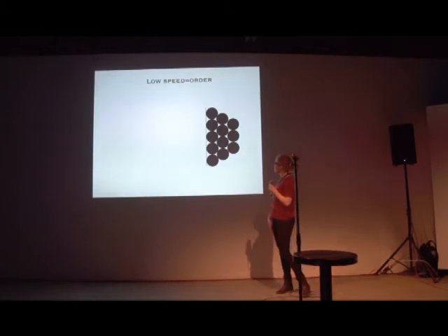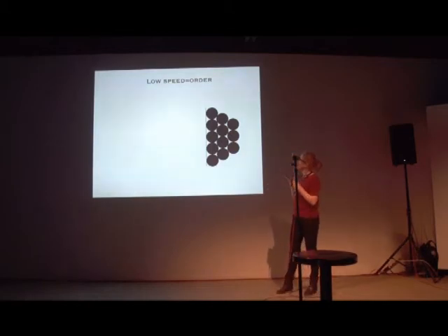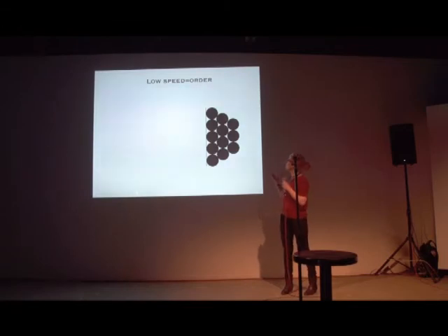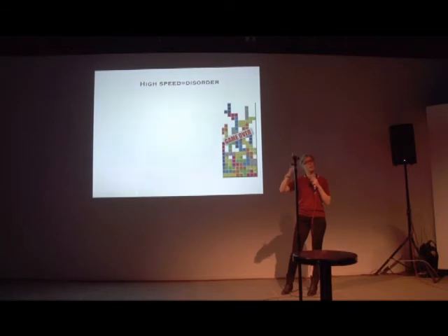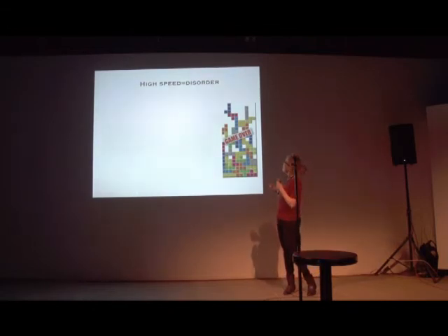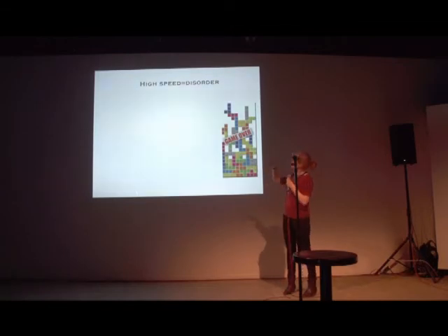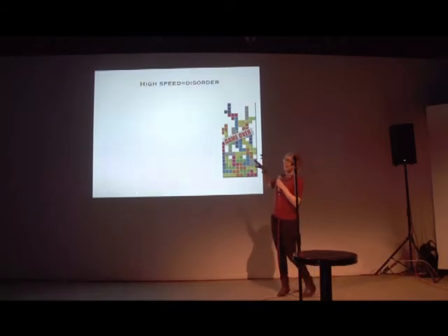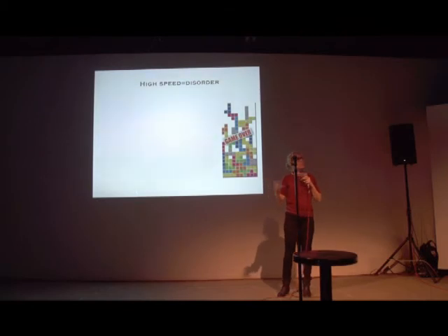In any case, what I wanted to explain here is how come that these particles can order. So if they arrive very early in the life of the drop, they have a lot of time to arrange. So when they arrive at the drop edge, they have time to explore space and to find the most efficient spot. So you get ordered packings. Whereas, so here you're supposed to see that when particles arrive very fast, then they don't have time for arrangement.